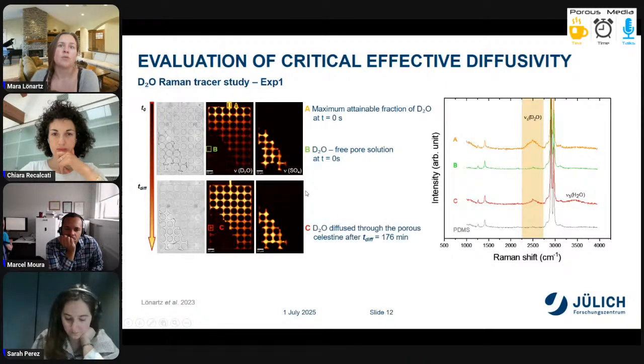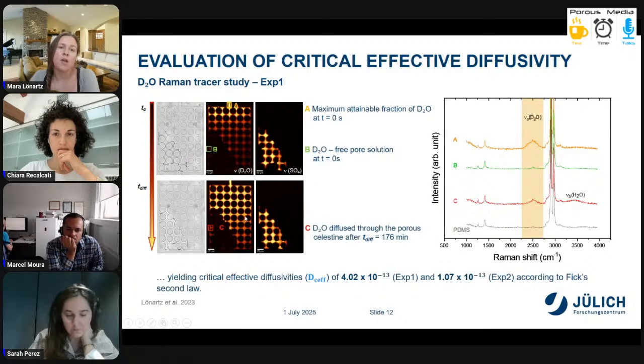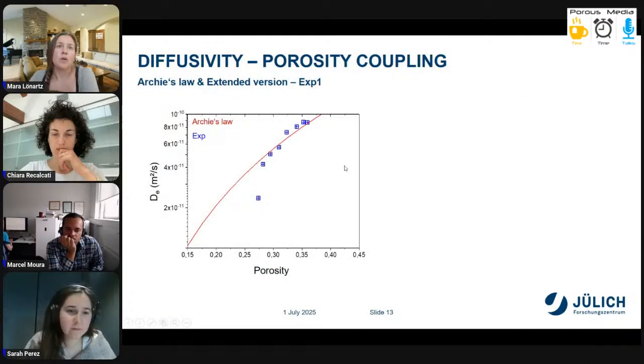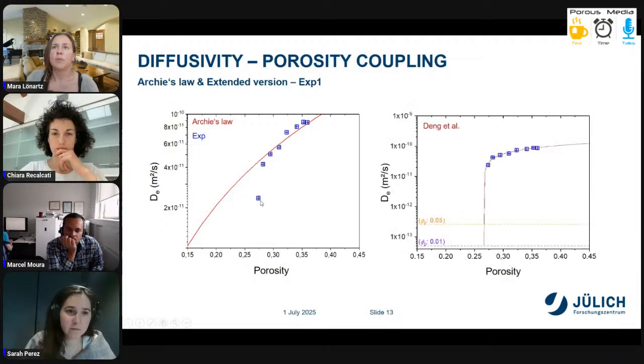And after around 170 minutes, we can see that the intensity on the other side of the precipitation front is also increasing for deuterium, which shows us that there is still a diffusive process going on, and which allows us to estimate a critical effective diffusivity, which was in the end of the same order of magnitude as proposed by Deng et al. Trying to reproduce our experimental results with Archie's law showed that the experimental results were deviating towards clogging, and then testing the extended version of Archie's law proposed by Deng showed a significant improvement.